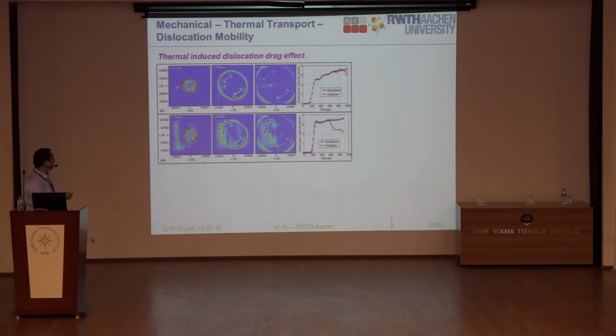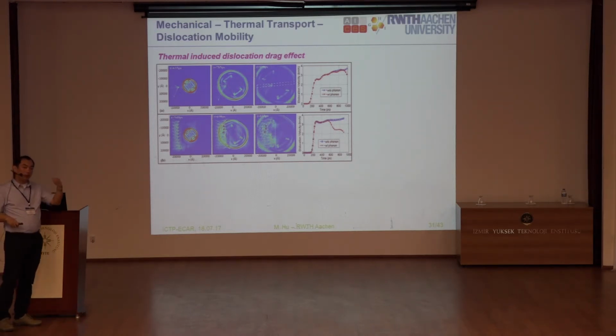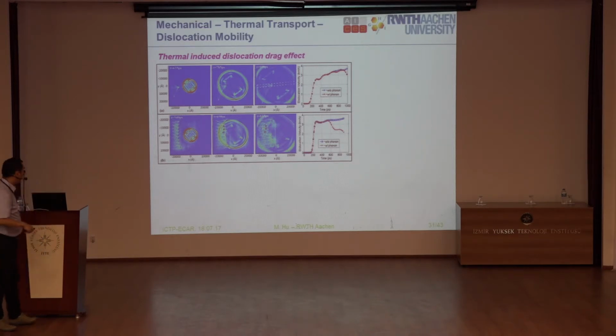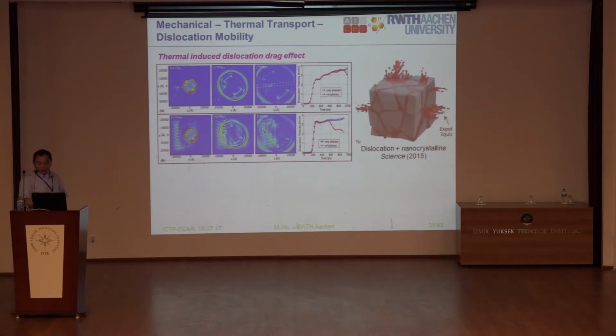We also know that in the literature, thermal gradients actually can induce this dislocation drag effect because of the phonon dislocation interaction. And if you talk about the mobility of the dislocation, if you have a temperature effect, the dislocation at the higher temperature moves more slowly than at the low temperature. So this is called the thermal dislocation drag effect. And in recent years, just a couple of years ago, this idea has been used for thermoelectrics.